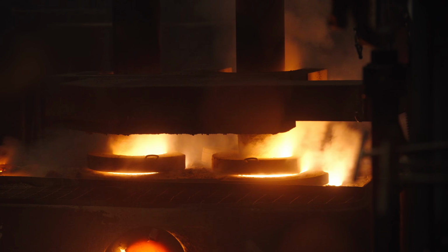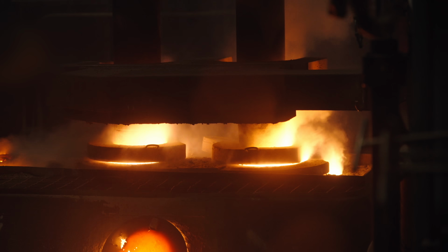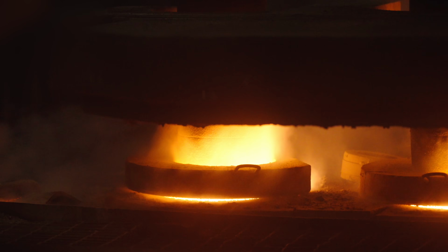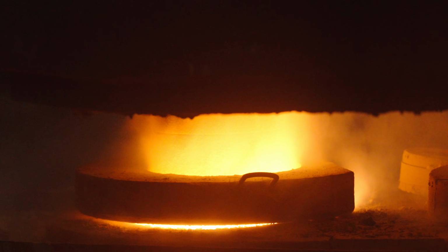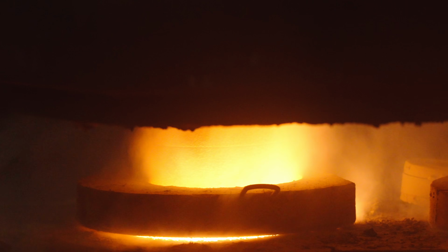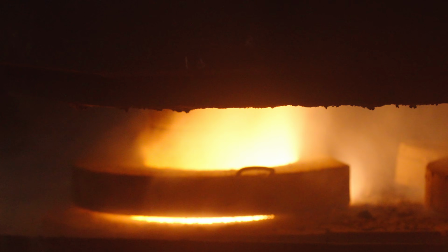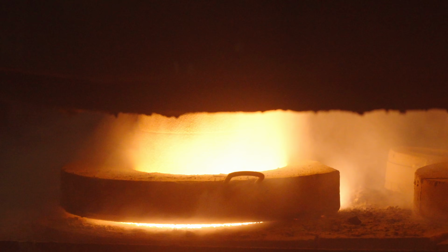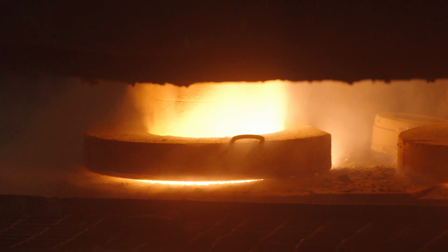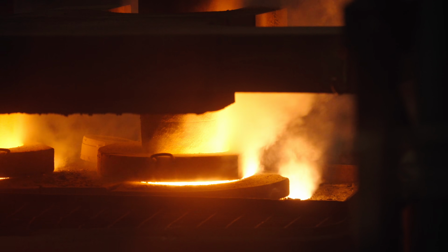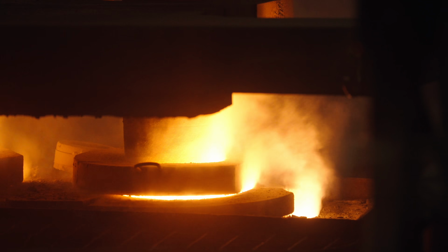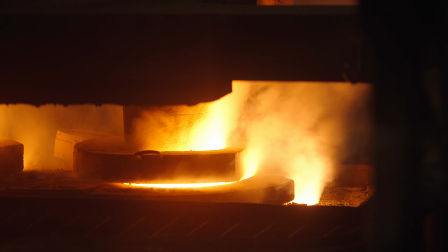Exactly. And if we look outside the window here, we can see that we have two graphite electrodes that are actually going through the lid of the tundish, and they're in contact with the slag layer sitting on top of the steel. Wow. So these are a measure to actually resistively heat the slag on top of the steel, keeping the liquid steel hot throughout the long atomization process.